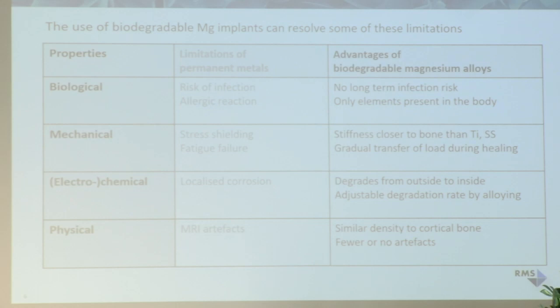On the stress shielding, I have to say that magnesium is much closer in stiffness to bone than titanium or steel. It has about 45 gigapascal, compared to about 15 for cortical bone. And what happens here is that with degradation, the implant carries less and less load. You also have a gradual transfer of load, and the tissue has to take over.